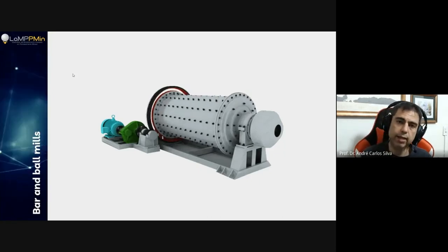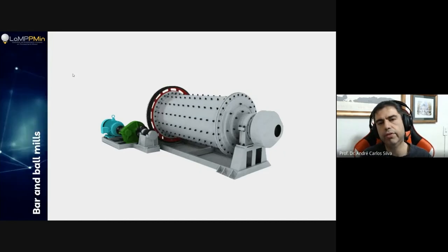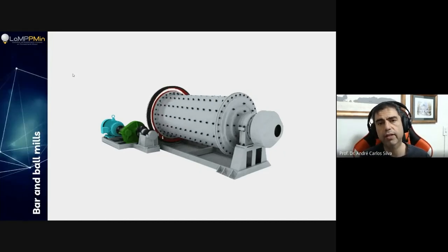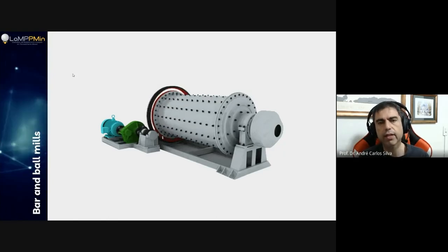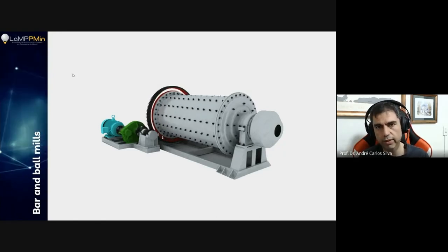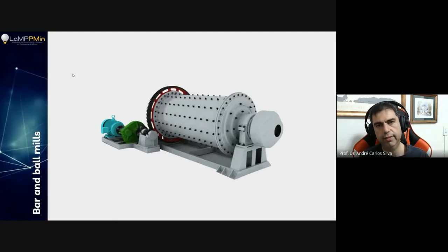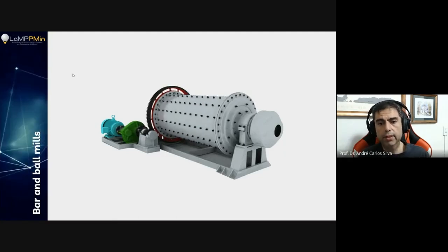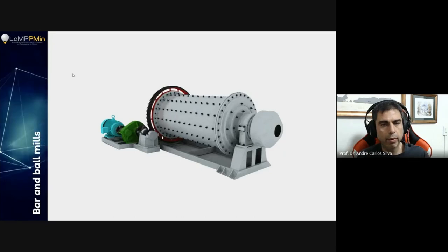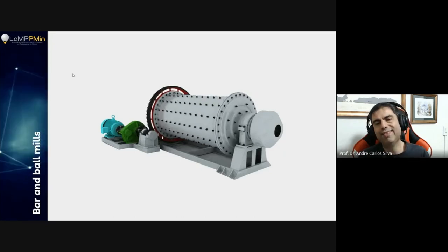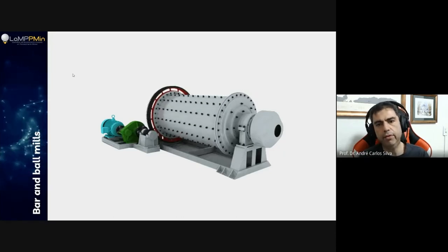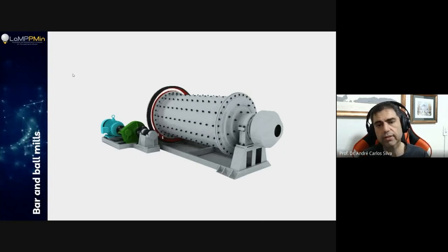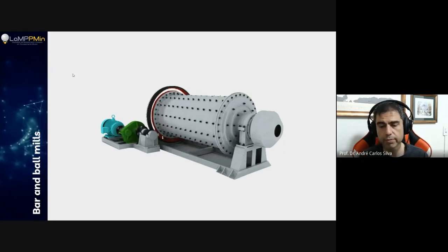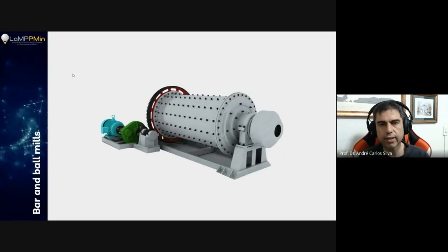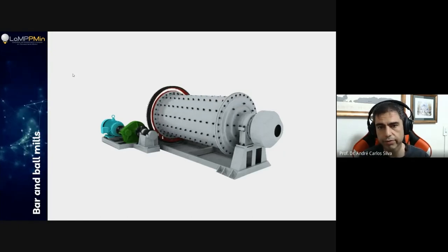And we can have the same geometry of the mills used with balls inside of it. Again, steel balls, but we can also have different grinding media, not only steel. I'm going to talk a little bit about that in a few minutes. But normally, when you talk about a ball mill, it would not be as wide as the bar mill, which means a little bit shorter than the rod mill, okay? But nevertheless, you can have this standard configuration for both of them.